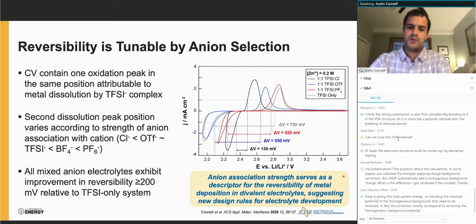These systems that we chose here certainly aren't optimized. There's a long way to go between what we have with these triflate and PF6 relative to what chloride can do, but we're moving in the right direction. And it suggests that we can really start to think differently about how we design electrolytes, where we don't have to get everything from one anion. We can start to design independently what's guiding one half reaction versus the other.